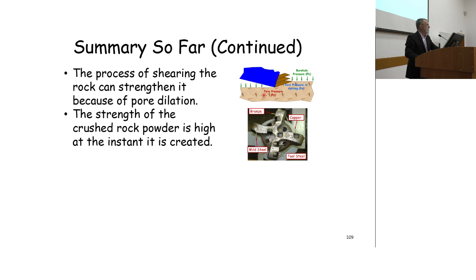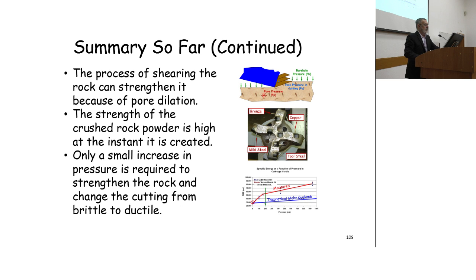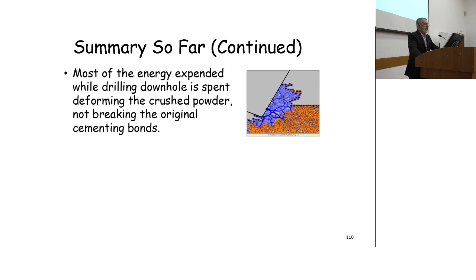We've shown that the strength of these cuttings is high at the instant that we make the cutting, and we've shown that it doesn't take a lot of pressure to cause the rock to be ductile. And finally, most of the energy expended down the hole goes into extruding the crushed material, not into breaking the original rock.